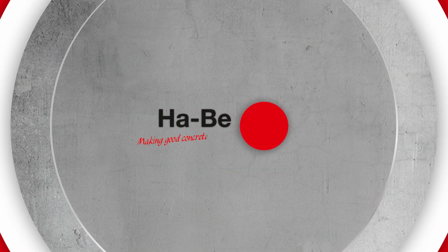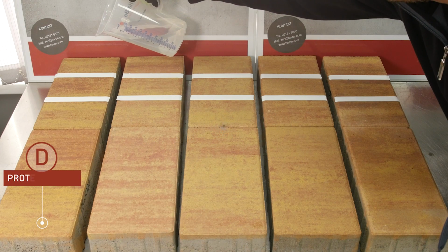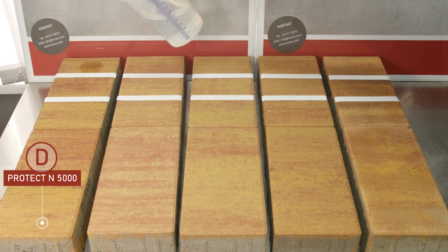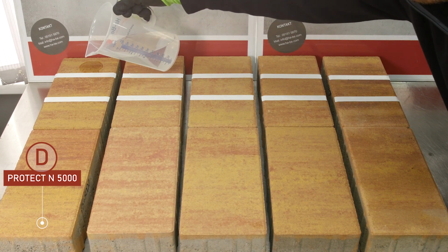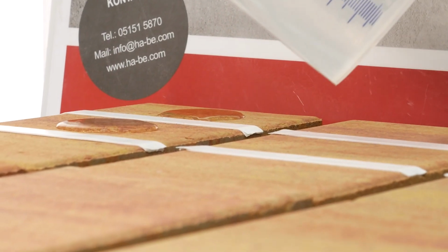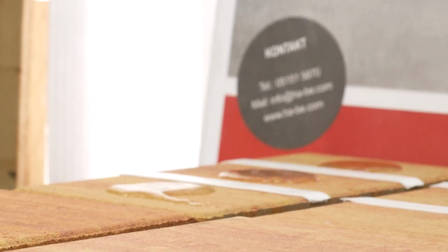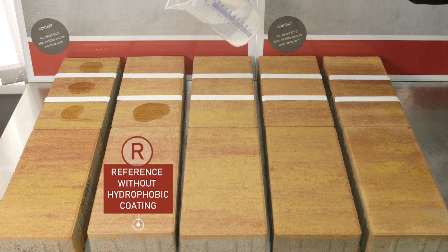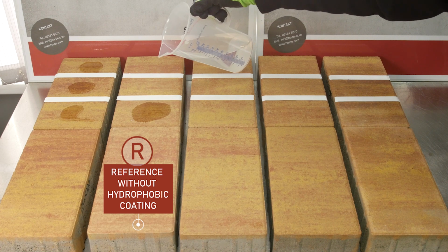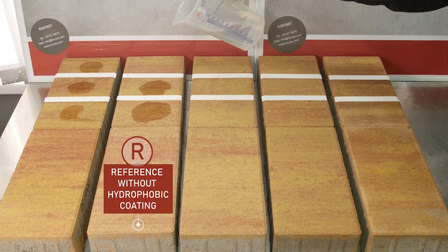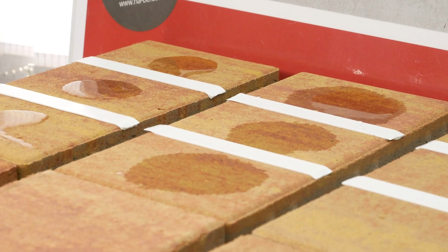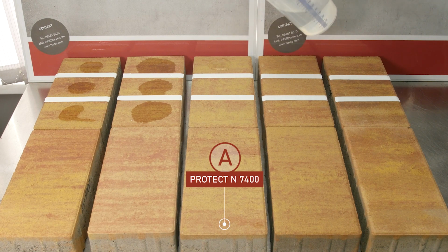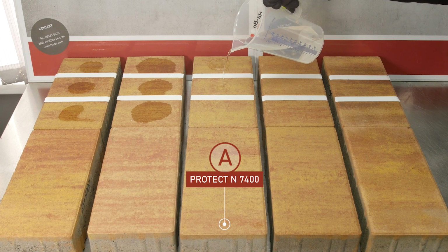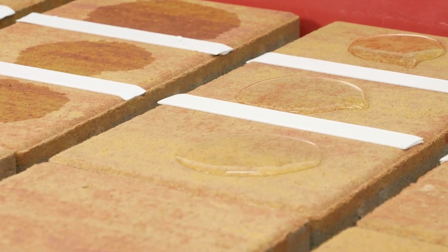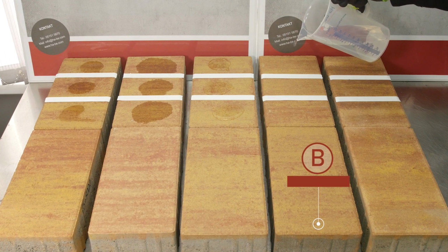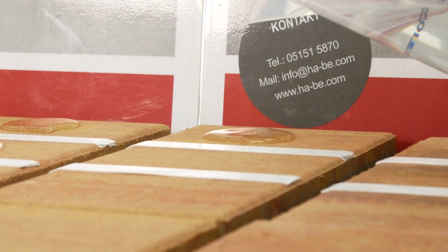Now let's see how water penetrates and a water spot forms after an instant water cleaning on the colour mix series. On sample 1, water breaks into pieces after pouring and doesn't penetrate into the concrete. On sample 2, reference, the water instantly penetrates the concrete. On sample 3, the water collects in a puddle and doesn't instantly penetrate the concrete. The same pattern is observed on samples 4 and 5.